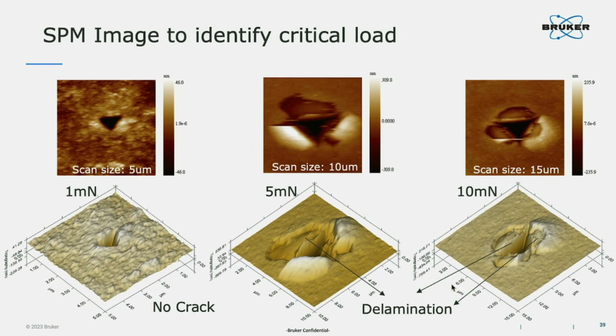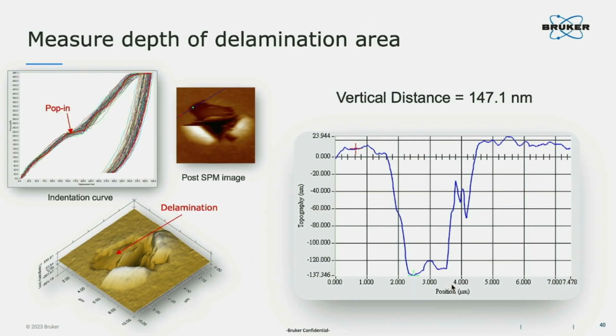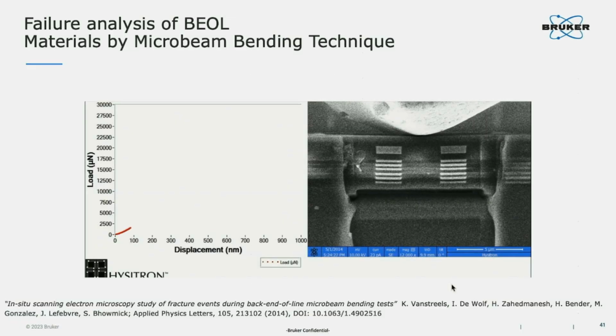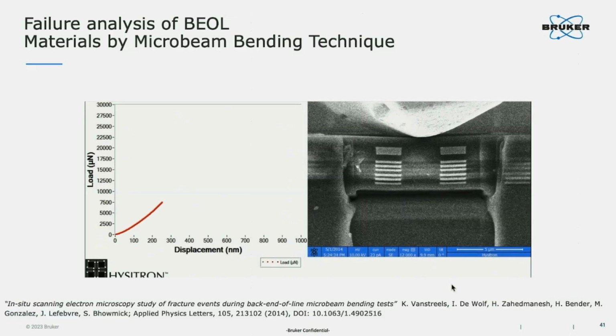So this is another example. This is about the same thing, right? When we indent, you see the delamination from the SPM image. So you can use the high-speed mapping to see the delamination signal. So mechanical properties, again, in situ is very important.